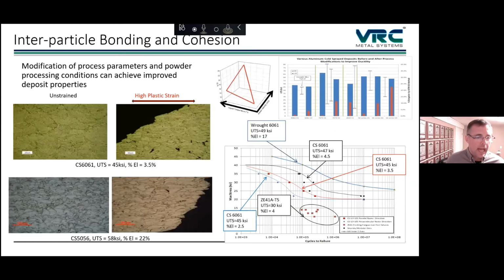And when you do that, you can see an example of a strained deposit on the right in these images, and on the left is the unstrained. And this is where ductility really comes into play. So when you build up these materials at very high velocities with lots of plasticity, you actually consume all of the interparticle defects, and that's how you get a high ductility material.